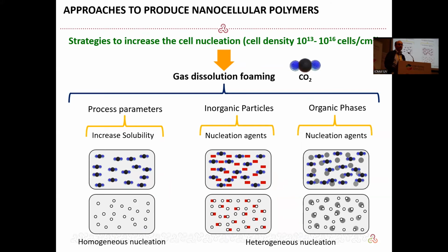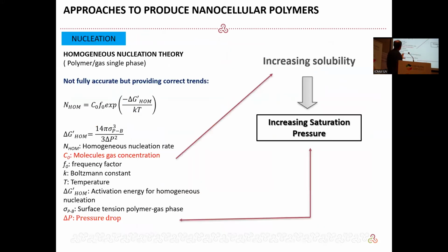There are two ways to create nanocells. One is by homogeneous nucleation, in which we use a pure polymer and we play with the saturation conditions: pressure, temperature, pressure drop rate. So it is, let's say, an approach based on physical parameters. And the second way is introducing nucleating agents into the material, so designing a formulation that chemically will create a very high number of cells very quickly.